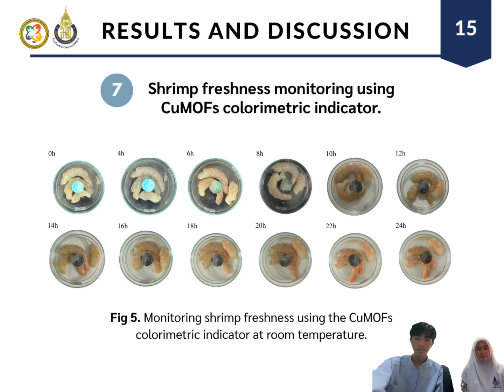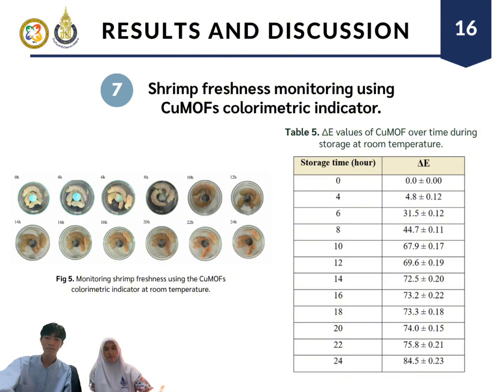For the result at room temperature, the delta E of the copper MOF colorimetric indicator increased with storage time, starting from 0.0 at 0 hour. In the 4 to 6 hour range, the indicator began to change color from light blue to green blue, with the delta E increasing from 4.8 to 31.5, indicating the start of shrimp spoilage. After that, the delta E continued to increase, reaching 84.5 at 24 hours, indicating more serious spoilage.